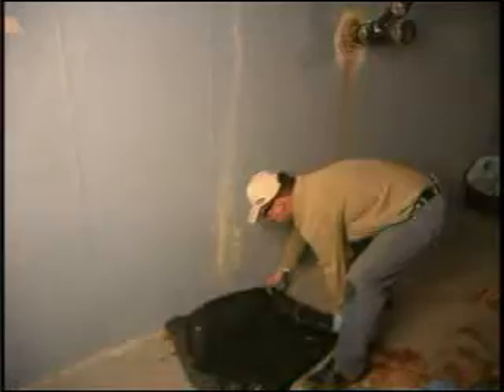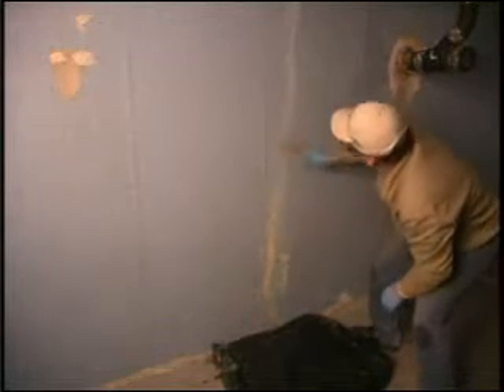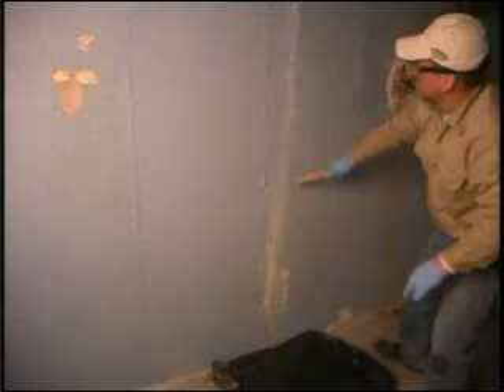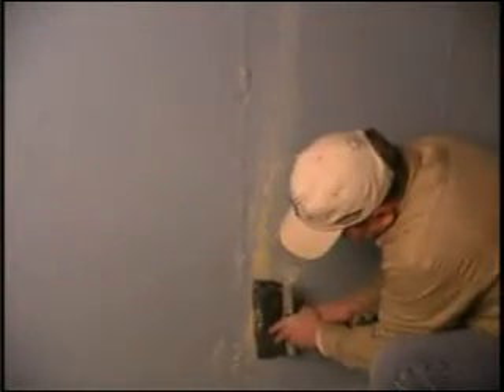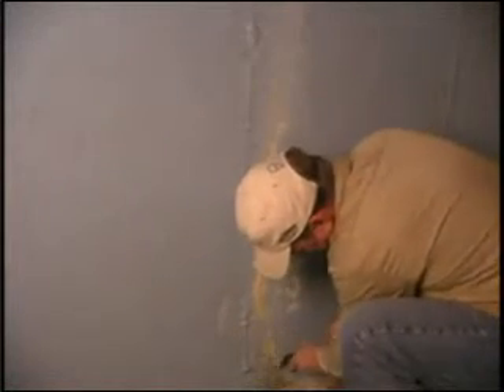Place drop cloth on the floor in front of work area. Clean the surface surrounding the crack using the wire brush. Remove loose or flaking concrete, efflorescence, paint, or coatings to approximately 1 to 2 inches on either side of the crack. The surface must be dry for proper installation of injection ports and surface seal.